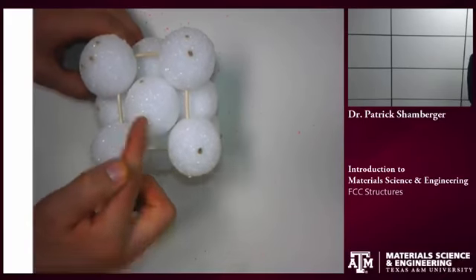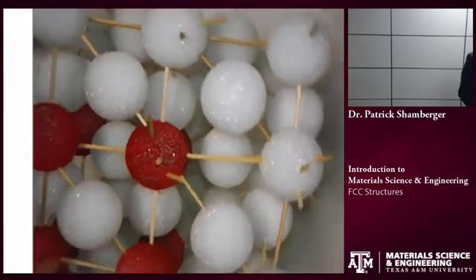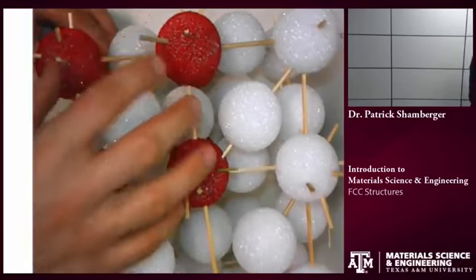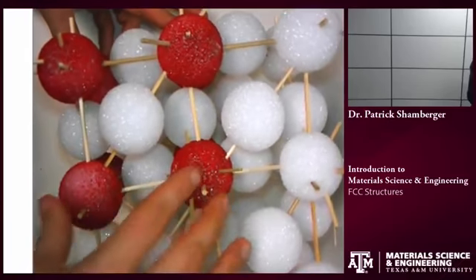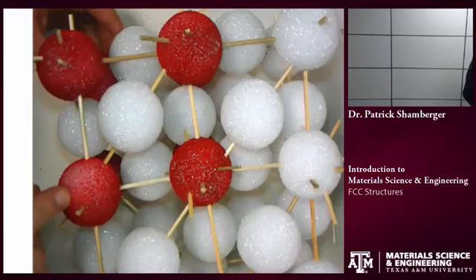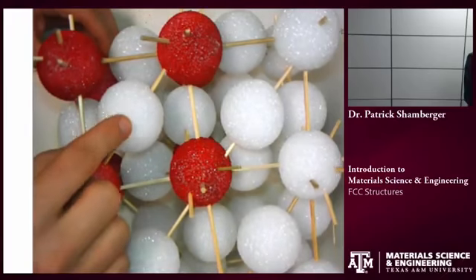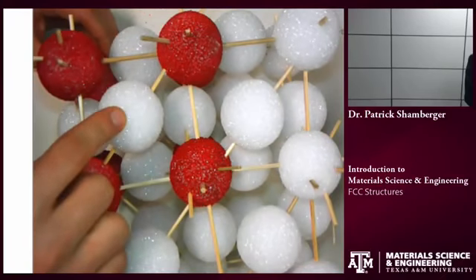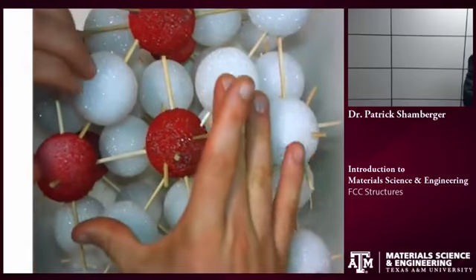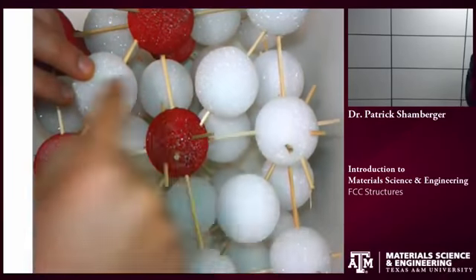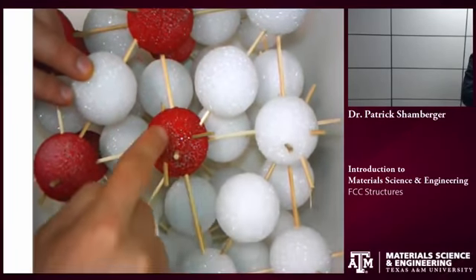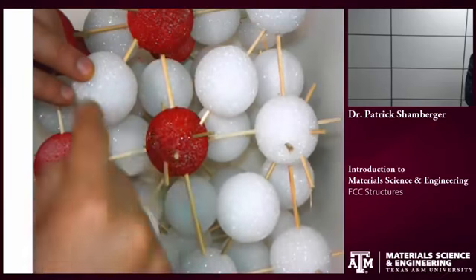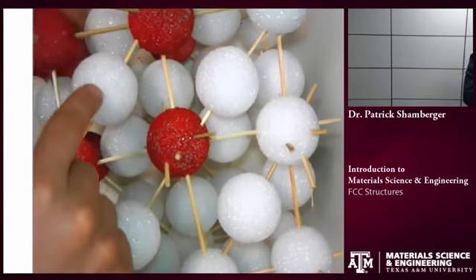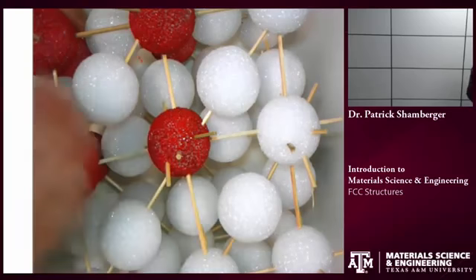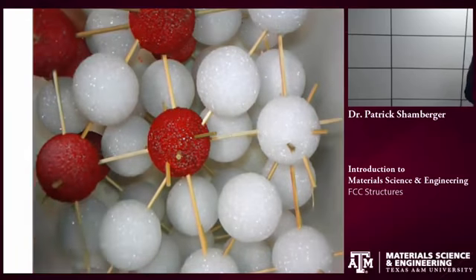For example, here we're going to switch models. If I take one face-centered cubic unit cell, where the corners have these red atoms, I see a lattice point on the center of that face. However, I could offset that unit cell, so now my corners are these white atoms, and what was a corner before is the atom in the center of the face. So even though this is in the center of the face and this is on that corner, they're entirely equivalent because they're all sitting on lattice points.